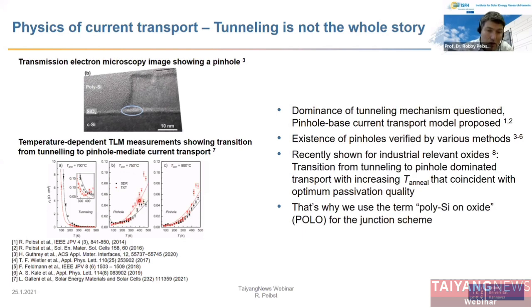And this was shown for all relevant industrial oxide types. And remarkably, this transition from tunneling to pinhole transport occurs at the annealing temperature which is the optimum for achieving the highest passivation quality. So in a well-annealed device, you will always have both pinholes and tunneling contributing together. And that's why we are using the term poly-Si on oxide, since it's independent of the current transport mechanism.